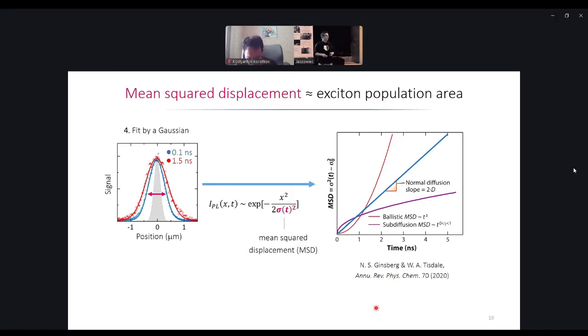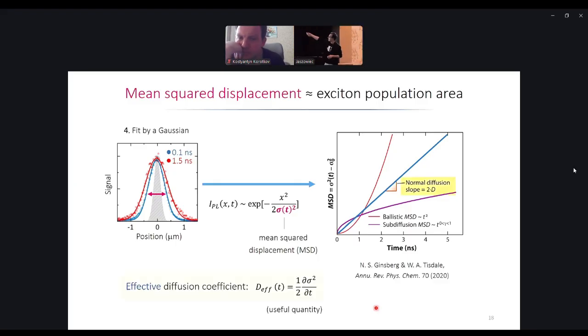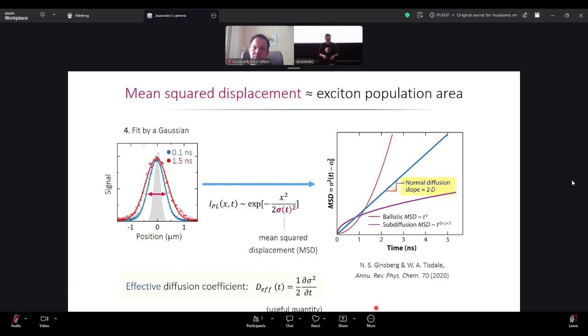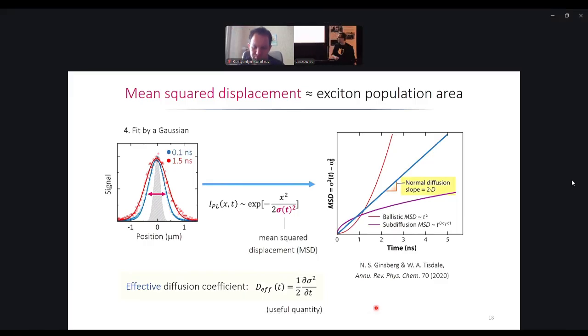Ballistic transport would look quadratic in this plot, so the area will increase quadratically, yeah, because then it means that we have a fixed speed of the particle. And there are many cases where you see subdiffusive behavior, which means your speed of the expansion is time dependent. Yeah? And these are kind of general regimes that you can find in this type of measurements. And sometimes it's also useful to define an effective diffusion coefficient, which may also be time dependent, by just taking a derivative. Sorry, a square is forgotten here. Oh no, sorry, it's wrong, it's fine. So you take the first order derivative to determine the effective diffusion coefficient.